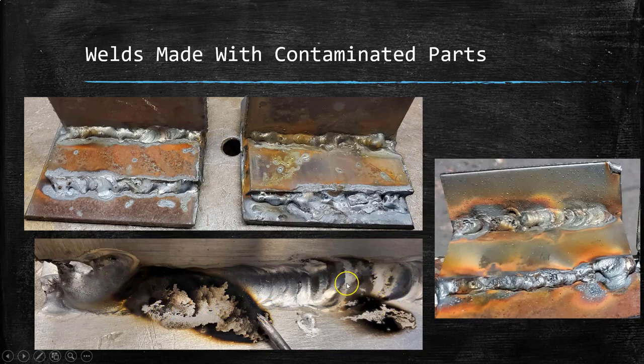So typically when you're welding aluminum, your weld should appear kind of shiny and metallic like this section right here, but contaminating the weld or contaminating the tungsten in any way is often gonna leave you with these soot marks or these white, kind of matted white appearances or spots. So here's a nice big area of contamination right here and right here.